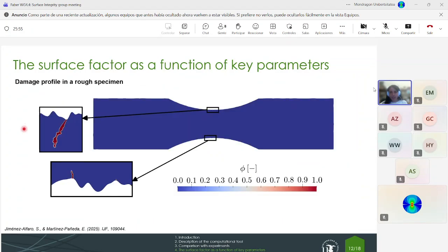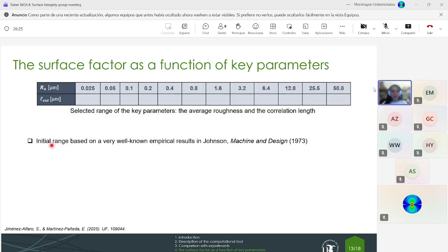But what is happening in the end with the phase field model? Here you have it. So the phase field damage starts in one of the peaks, 1, 2, 3, the ones that arrive to the failure, and then the cracks propagate towards the center of the specimen. Then since we are under force control, when a certain region in the specimen is covered by a damage equal to 1, then we consider that the specimen has failed, and then we determine the number of cycles to failure.